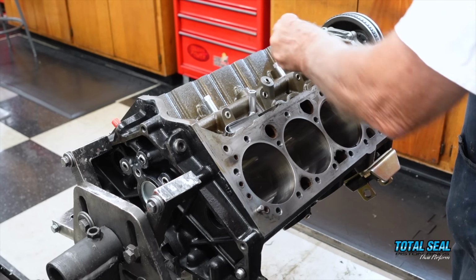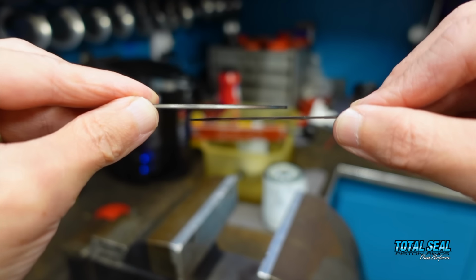So one other difference between the Engine Masters test and our test is when they went from that 5/64th ring, basically a 2 millimeter ring, down to that 1.2 millimeter ring, that's a change of 31 thousandths in ring size. We're going from a 16th ring to a 0.9 millimeter ring. That's only 27 thousandths change in size. So they had a little bit bigger change than we did. Again, we're not gonna know until we finish putting the engine back together with our nice handy dandy gas-ported 0.9 millimeter rings to see how much of a difference our test does compared to their test.